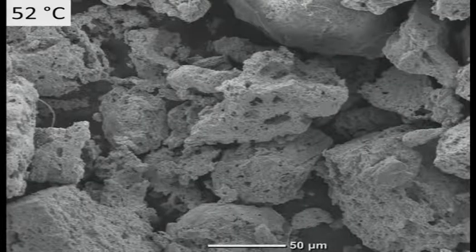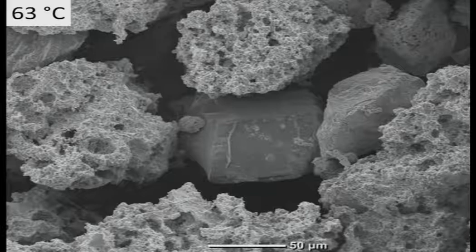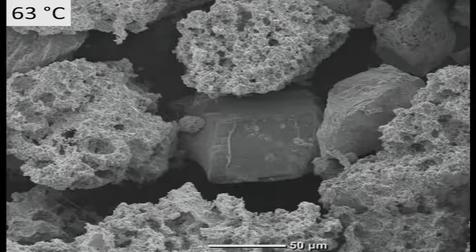By about 52 degrees, the residues had started appearing quite porous, but with a few particles that looked otherwise intact. So the surface is quite a bit more severely attacked in these conditions, 100 grams per litre sulfuric acid, 52 degrees, but there are a few particles that appear intact, and the contrast is a bit more obvious in this one. At 63 degrees, we've got a bunch of very corroded looking particles around the edge, with a few, like the ones in the middle, that seem relatively intact, which either survived the leaching process or formed during it.